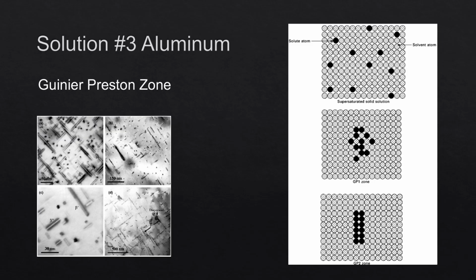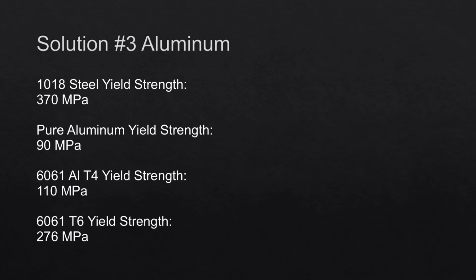As they are coherent with the aluminum structure, their mismatching radii cause strain in the surrounding lattice, which in turn opposes dislocation slips. This type of heat treatment and aging process is what gives aluminum its high strength-to-weight ratio, meaning less material mass is required for a given specification, increasing its sustainability.